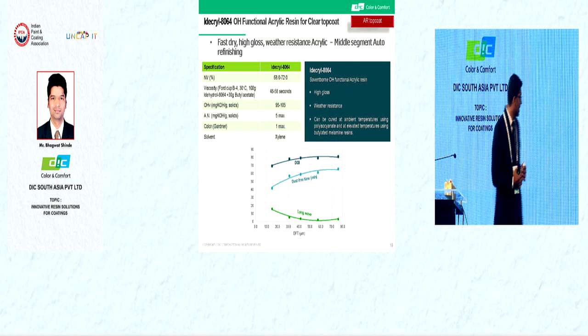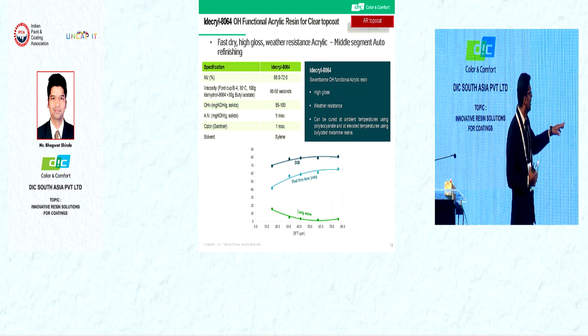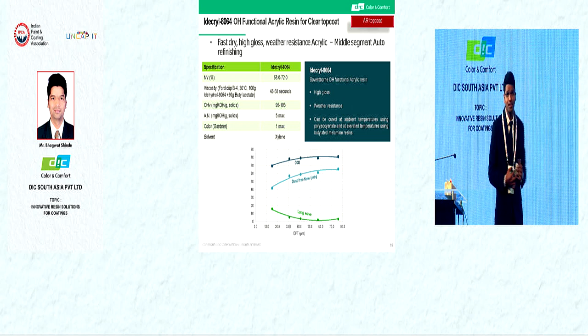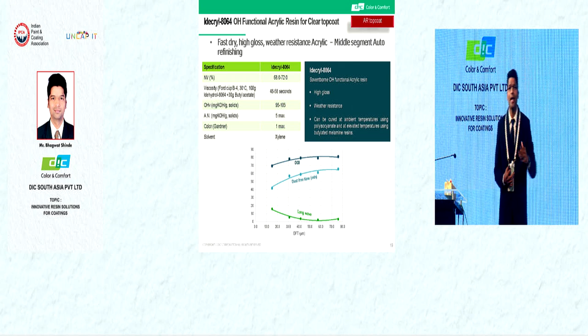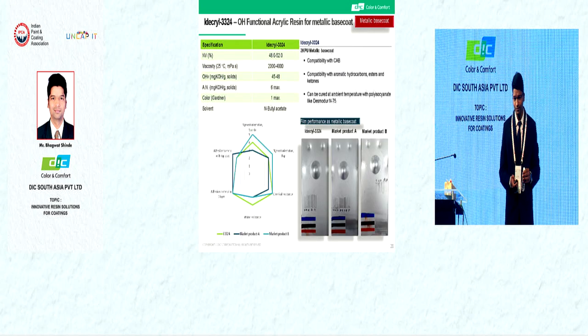As you see in the graph, at 50 micron DFT, the DOI of the film is around 80 or 80 plus. That means this product shows good leveling and gloss properties.